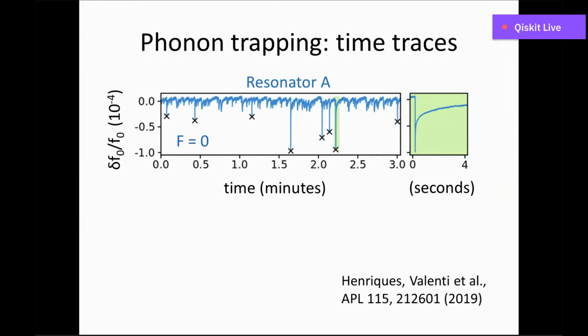What I show here is the time evolution of the resonant frequency of resonator A for our control sample without phonon traps. We observe the quasiparticle bursts that I mentioned before. And if I zoom into one of them with the gray square, we can appreciate their relaxation time of the order of 1 second. What happens if we had phonon traps?